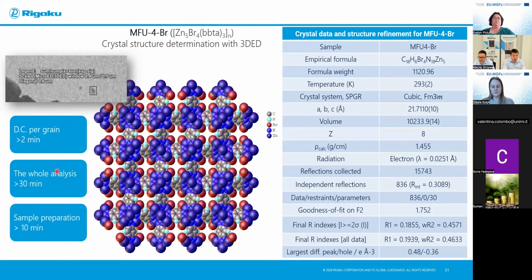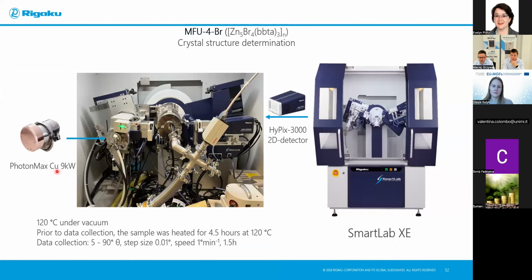We have lots of documentation on it if you want to learn more, to understand better how you use electron diffraction and how you collect data. But generally, it's a very easy and available technique, already using an electron diffractometer and not a dedicated microscope for electron diffraction. Yes, exactly. And the crystal model, which Jakub obtained after the analysis of the data from electron diffraction, I used later for Rietveld refinement to check the bulk sample, and also to prove the purity of the compound.